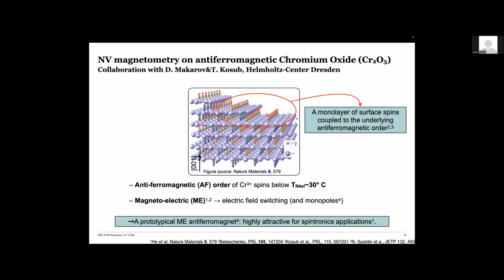But I do want to maybe also highlight one recent result, and I'll be fast, on studying this antiferromagnet chromium oxide, Cr2O3, which is a rather interesting material system for implementing antiferromagnetic spintronics technologies. That's on one hand because this is a material that orders at room temperature, but more importantly, it is a magnetoelectric antiferromagnet, which means that you can actually manipulate the order parameter using electric and magnetic fields. And as it turns out, the fact that it's magnetoelectric also brings with it a very nice property, namely that there are uncompensated spins on the surface of this material, whose direction is linked to the direction of the underlying Néel vector, and therefore allows us to address this material.